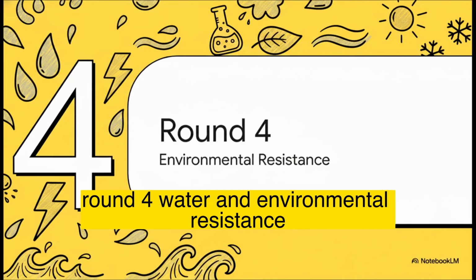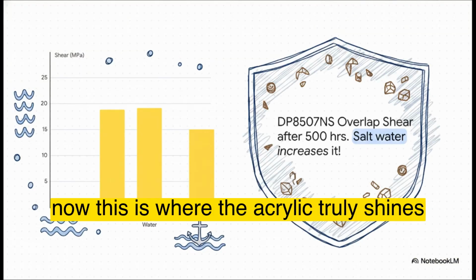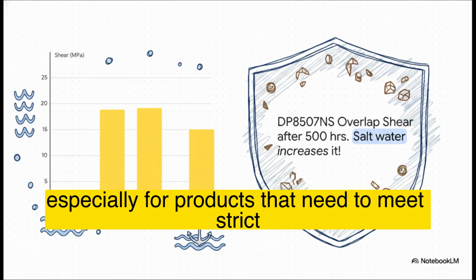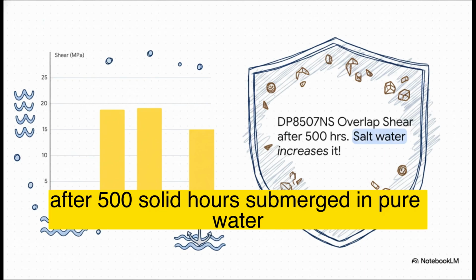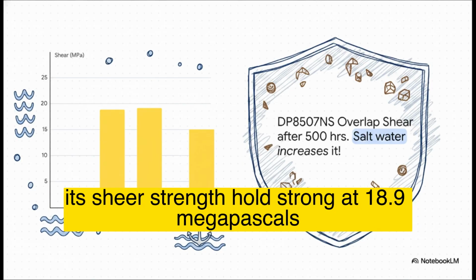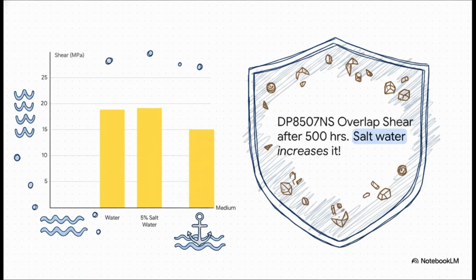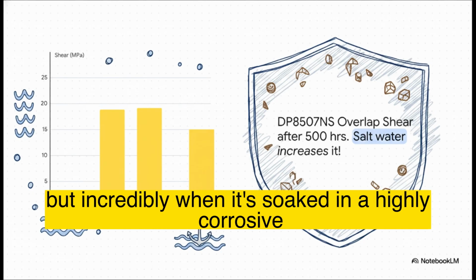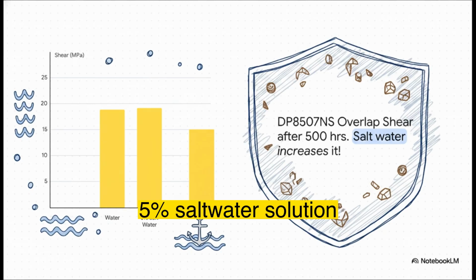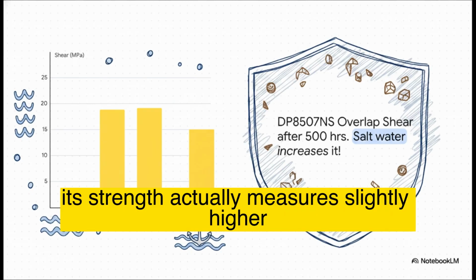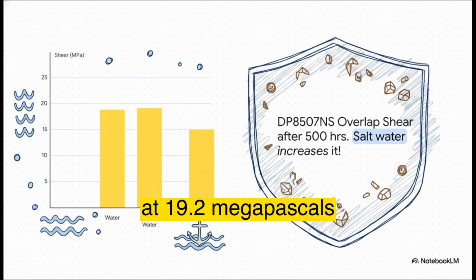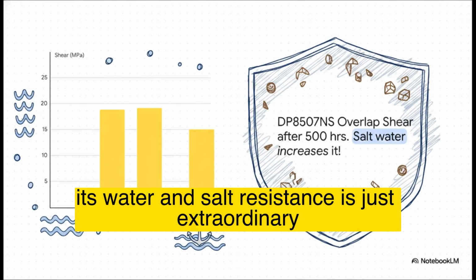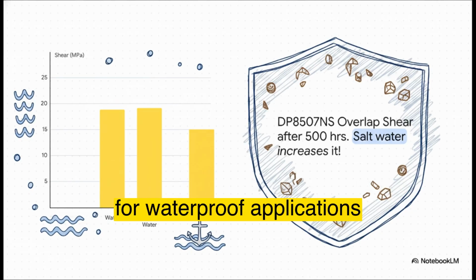Round 4. Water and environmental resistance. Now, this is where the acrylic truly shines, especially for products that need to meet strict waterproofing standards. After 500 solid hours submerged in pure water, its shear strength holds strong at 18.9 megapascals. But incredibly, when it's soaked in a highly corrosive 5% saltwater solution, its strength actually measures slightly higher at 19.2 megapascals. Its water and salt resistance is just extraordinary for waterproof applications.